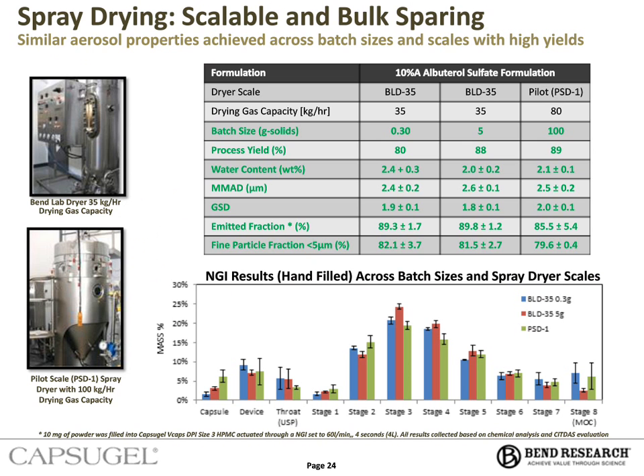And so the spray drying process truly is a continuous process. So it's usually dictated by your starting solution volume. So what we see here is a good process yield, which obviously increases with larger batches and encroaches into the 90% range. Similar water contents achievable across scales. And then the aerosol performance results. So the mass median aerodynamic diameter shown there, the standard deviation or span of the distribution, the emitted fraction, and the fine particle fraction, which will be used throughout this case study for comparing the different formulations.